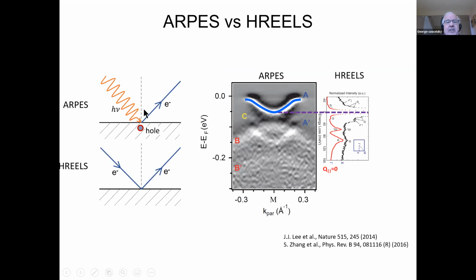In photoemission, you have an electron coming out. Now, the reason why this is interesting is because there are high-resolution electron energy loss experiments done where you shoot an electron in on the same system and scatter it more or less specularly and look at what the energy loss is. And that energy loss spectrum is shown on the right-hand side under the HREELS, okay? So this is the zero loss line here.